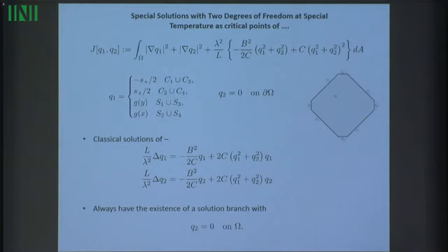on a square domain subject to Dirichlet boundary conditions, and mathematically this is equivalent to studying solutions of this system of coupled elliptic partial differential equations with just one parameter lambda, which is the size of your square. Some of you will recognize this to be the Ginzburg-Landau PDEs in superconductivity, which means that you can use a lot of results.